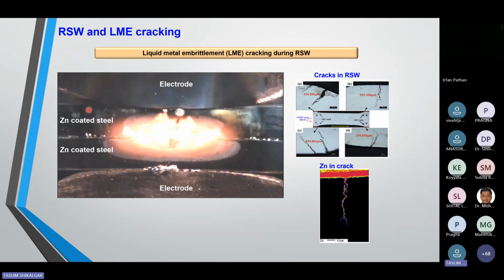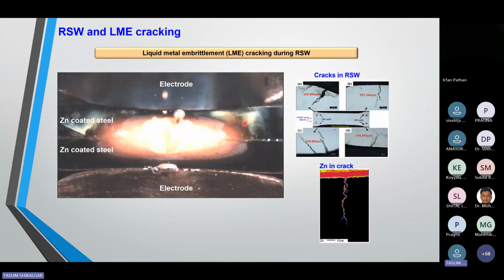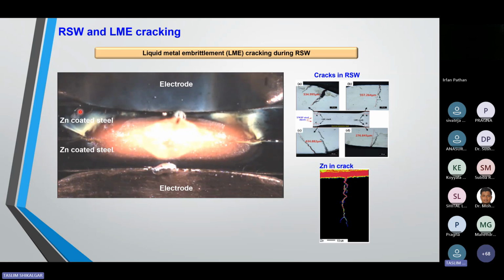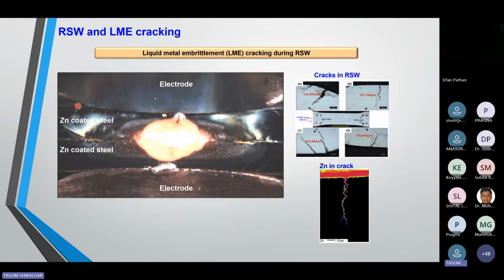Here you can see carefully. You can observe this zinc is going inside and generating the cracks here also. Like you can see carefully, here a crack is generated, here a crack is generated, here also a crack. You can see multiple cracks observed during this. So this is one of the important challenges, how we can find out the crack locations as well as how much is the crack depth and how dangerous this crack is, because people want to test this type of BIW during an accident, how much impact this crack has, because safety is the important factor for any automotive manufacturer.